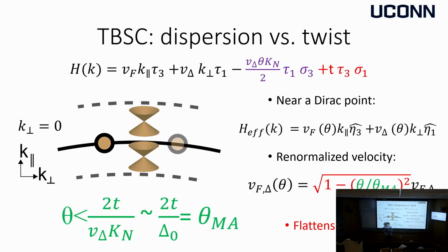Notice that those Dirac cones are not isotropic. They can be horrendously anisotropic. The velocity in two directions can be 10 times different, but they are renormalized in exactly the same way. And that just falls out of that equation. The magic angle in this case is equal roughly to the ratio between interlayer tunneling and superconducting gap, the maximum superconducting gap in each layer. So let's say for cuprates, that's a very small quantity. And I will show that the estimate for this magic angle is around 3 degrees compared to 45 degrees I've been talking about in the first part of my talk.